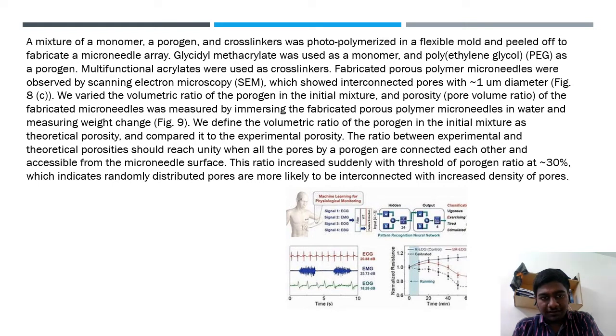We varied the volumetric ratio of the porogen in the initial mixture, and the porosity of the fabricated microneedles was measured by immersing the porous polymer microneedles in water and measuring the weight change. We define the volumetric ratio of the porogen in the initial mixture as the theoretical porosity and compared it to the experimental porosity. The ratio between experimental and theoretical porosities should reach unity when all the pores made by the porogen are connected to each other and accessible from the microneedle surface.